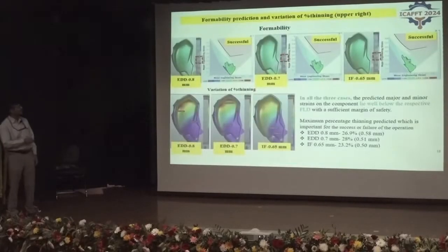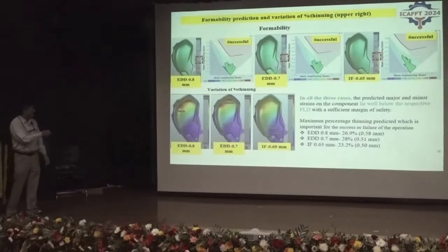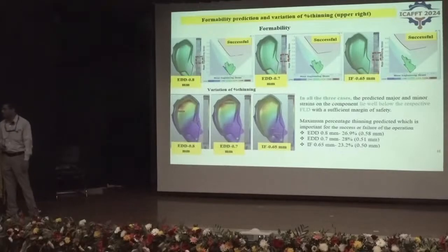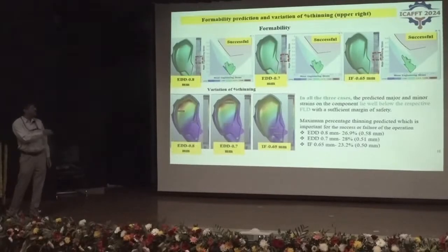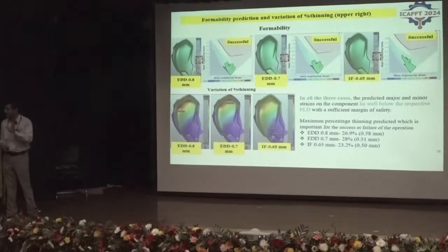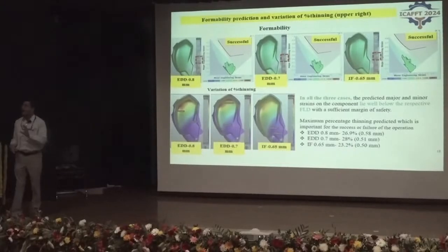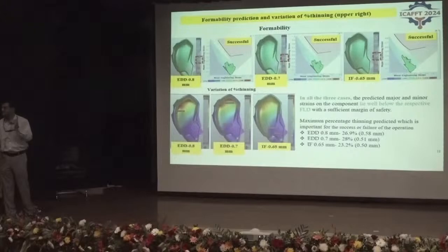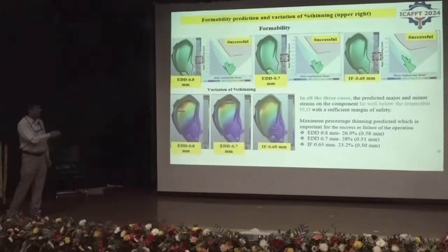And here you can see some simulation results of the two-wheeler fuel tank. Initially we started with EDD 0.8 mm, just to validate the existing data, and iteratively we reduced the sheet thickness without changing the grade, and we went down to 0.7 mm. Still the operation was successful, and the strains on the component predicted were much lower than the forming limit curve, and it clearly shows that we can go down to 0.7 mm. One of the major requirements is that in the final formed part, the minimum thickness at any location cannot go less than 0.5 mm. So that was one of the requirements apart from the other things.